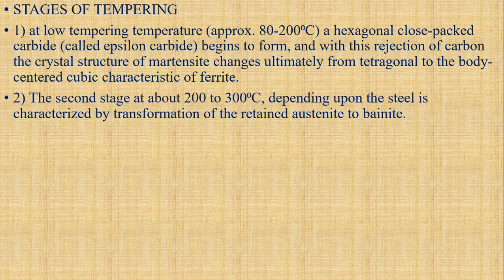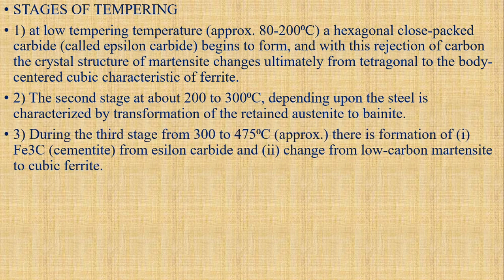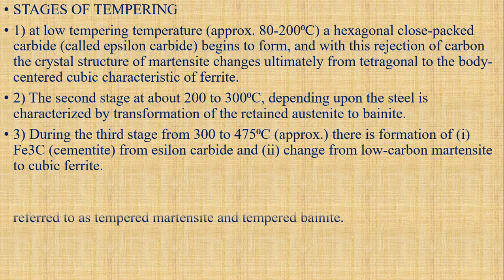The second stage, at about 200 to 300 degrees Celsius depending upon the steel, is characterized by transformation of the retained austenite to bainite. During the third stage, from approximately 300 to 475 degrees Celsius, there is formation of Fe3C cementite from epsilon carbide and change from low carbon martensite to cubic ferrite.